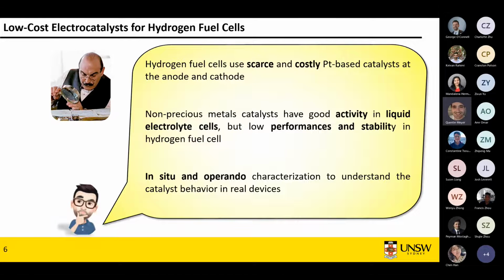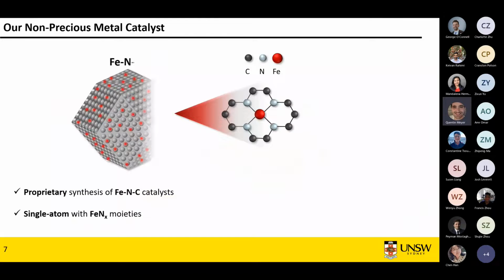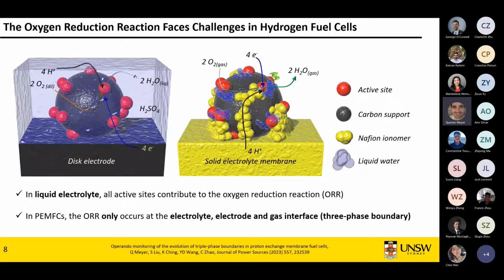So why does that happen? The best way to find out is to go in depth and do in situ and operando characterization to understand the real devices. So we've developed our own iron-nitrogen-carbon catalyst. The synthesis is confidential, but overall, what we're fairly confident of is that we have a single-atom iron-nitrogen-carbon catalyst with FeNx moieties.